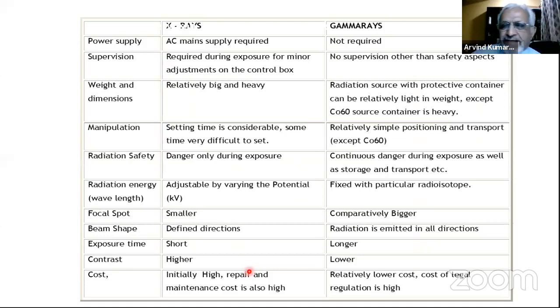Now, some differences between X-ray and gamma ray. Again, I will not go into too much detail, because we know X-ray we can control. We are not totally exposed to the radiation all the time, whereas with gamma rays you are exposed all the time. X-ray gives high contrast and good definition, whereas gamma radiography gives slightly inferior sensitivity. The source focal spot is the governing factor. The smaller the focal spot, the better the X-ray sensitivity that you are going to get.